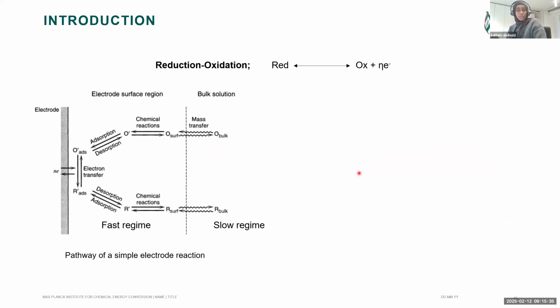Here I show you a schematic diagram of all the different processes that can happen on the electrode. This is an example of solution electrochemistry where your species of interest is either oxidized or reduced by the electrode. You could have adsorption and desorption going on in your system. Chemical reactions could occur once the species is further away from your electrode, and then also mass transfer. What's going on closer to the electrode we can refer to as a fast regime, and further away in the bulk solution as a slow regime.